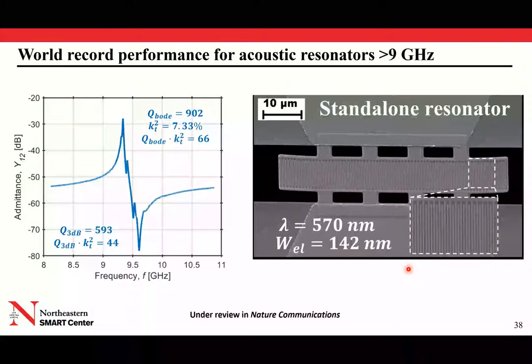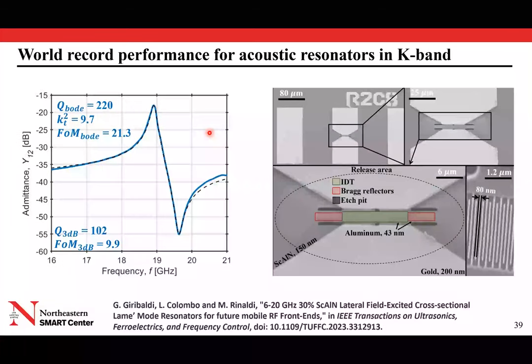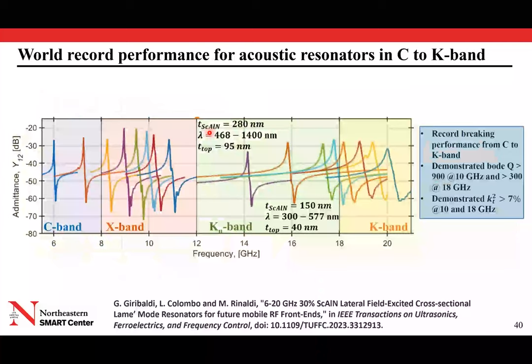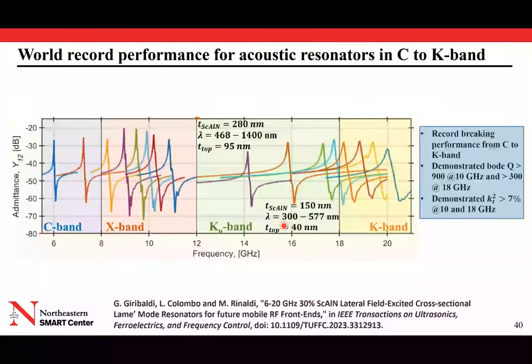So here are some of the results that we have. You see here, there's a micromechanical resonator operating at around 9.5 gigahertz. It shows an electromechanical coupling coefficient of over 7% and a quality factor of about 900, which is very exciting. And we scale up also at higher frequency. So here you see around 19 gigahertz, we got Kt squared approaching 10% with a Q factor larger than 220. And so we really built devices across the whole spectrum, from 6 to 20 gigahertz, which is something very exciting. We did that using just two substrates basically, right? Because we have the lithographic tuning capabilities.